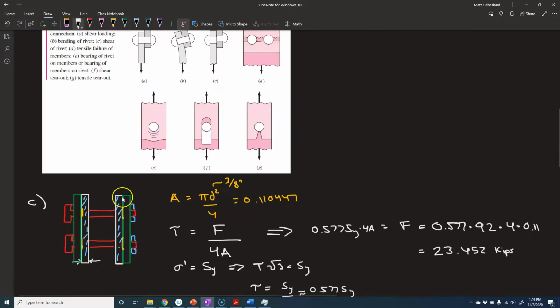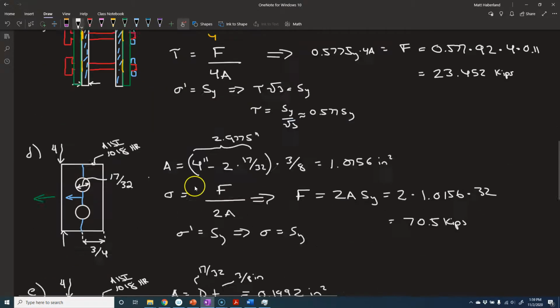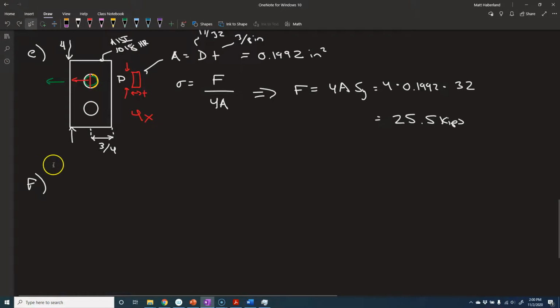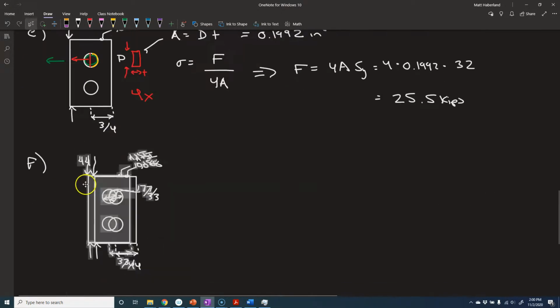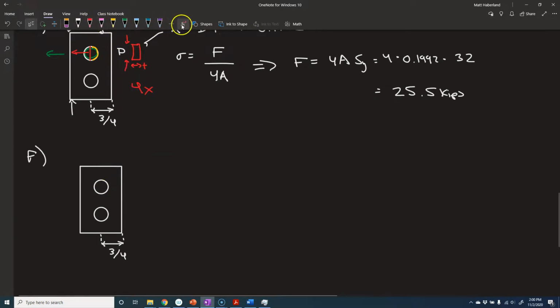So last thing that we're going to analyze is kind of this shear tear out. This tensile tear out is not something that Shigley gives us a way of estimating. You'd have to somehow find whatever the stress perpendicular to this surface is, and that's kind of tricky. So we're just going to analyze this one. And again, I think the best cross section to use is this one here. I'll copy it from above. We're talking about failure at this surface. We underestimate kind of the area. We say, all right, where is the closest distance between the edge of the hole and the edge of the part? So it's going to have to tear here, here, here, and here at the same time.